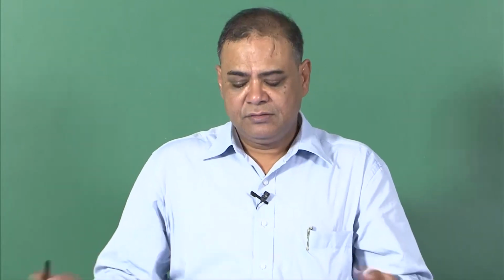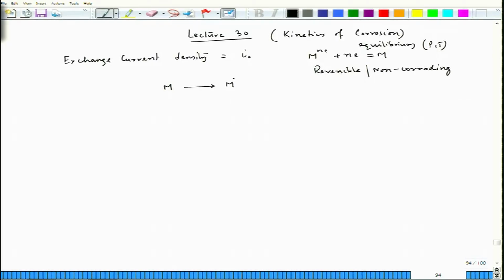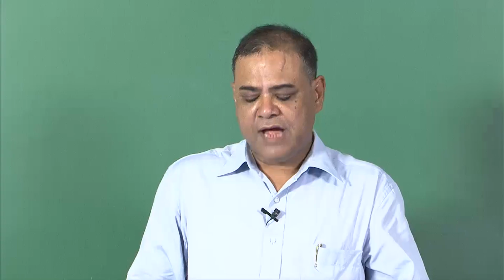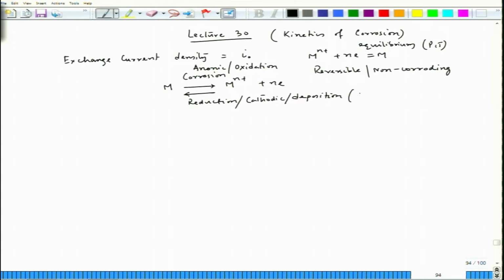The metal ion formation, which is M goes to M^n+ plus ne, this is corrosion, or we can take it as the anodic reaction or oxidation reaction. And then this backward reaction is reduction, or cathodic reaction, or deposition reaction. Both these processes happen at the same rate, and the rate is termed in terms of i0, the exchange current density.